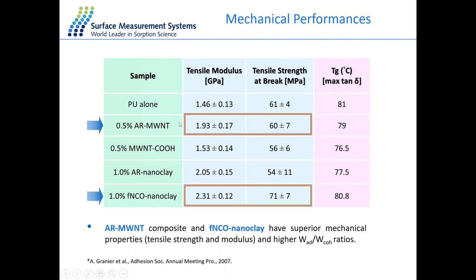And we find that the untreated nanotube sample and the treated nanoclay sample have the better mechanical performance compared to the other fillers. This is very consistent with our prediction that the untreated nanotube and the treated nanoclay will have a better adhesion with the polymer matrix. So that means we can use IGC to predict this kind of mechanical performance in the formulation design, to choose which kind of filler has the best affinity with the matrix sample.